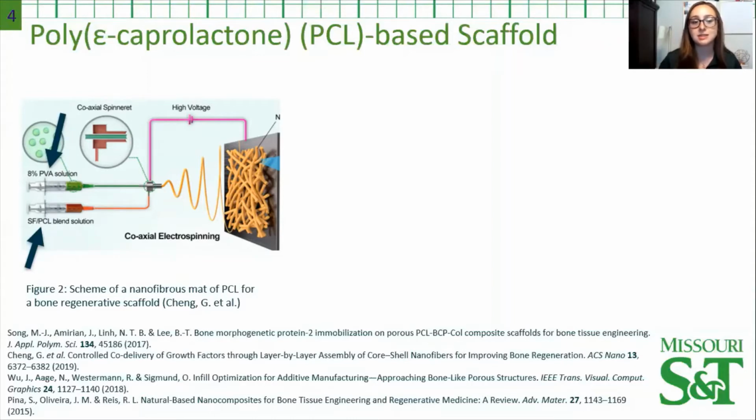electrospinning. Cheng's study is an important design of a dual growth factor system that can provide some framework for the biomaterial. Electrospinning is used to prepare nanofibrous mats or scaffolds, which are beneficial in cell attachment and are a good surface for focal adhesion proteins. They also have high porosity, mechanical stiffness, and gradual degradation, which is beneficial in a bone scaffold.